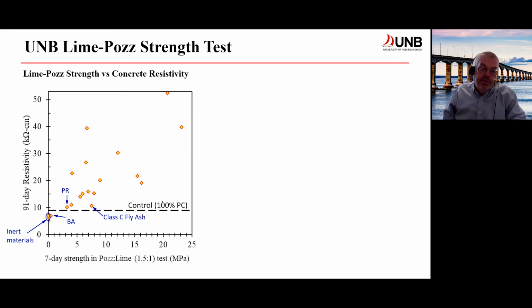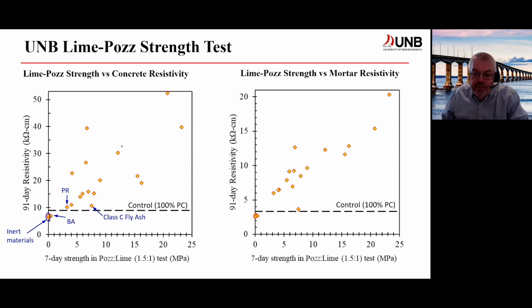Electrical resistivity provides a very good measure of the performance of a pozzolan. And if we did want an indirect measure of a pozzolan's ability to perform well in concrete, then concrete resistivity would in fact be a way to go. And again, this is showing a relationship between resistivity of mortar cubes made with cement pozzolan mixes and the 7-day strength of our lime pozzolan test on the horizontal axis.